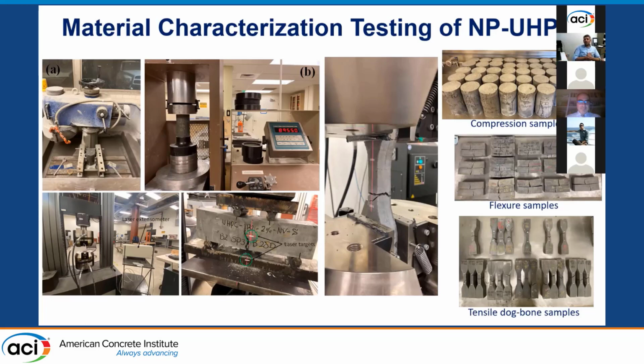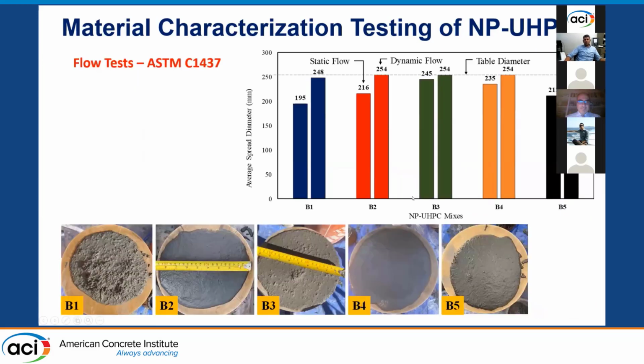Most of the analytical equations have been verified for proprietary and high-end UHPC. So we wanted to see if these are valid for non-proprietary mixes or lower-end types of mixes as well. So we started with the flow, especially that we had, you can see here, that's the unsieved one. All of them, in terms of meeting the ASTM 1437, are acceptable in this range.